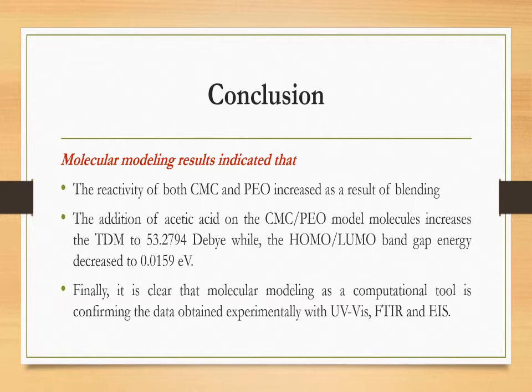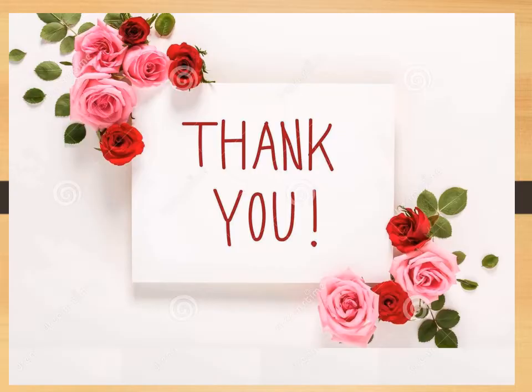And finally, it's clear that molecular modeling as a computational tool is confirming the data obtained experimentally using ultraviolet visible spectrophotometer, FTIR, and electrical impedance spectroscopy results, which confirmed that the prepared solid polymer electrolytes and the proposed model molecules representing CMC and PEO become more sensitive and can be used in sensing devices as a membrane material.